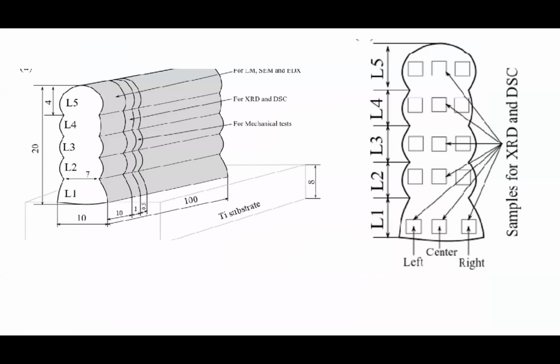In order to get a metallurgical grounding, we had a collaboration with a Russian university, St. Petersburg University. They have been working on powder metallurgy based NiTi structures, so they have a strong background in the metallurgical aspects of shape memory structures. We collaborated with them to understand the mechanism of what is happening. As a first level of understanding, we made some 5-layer structures. This is a panoramic cross section of the 5-layered sample. For convenience, the layers were numbered from bottom to top. The first layer was the layer deposited on the titanium substrate, and the 5th layer was the last layer deposited.